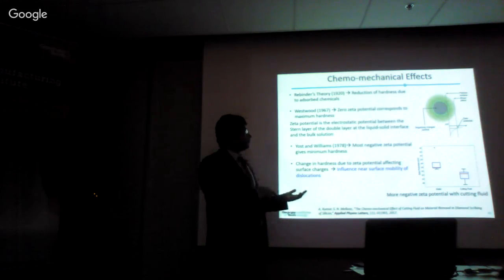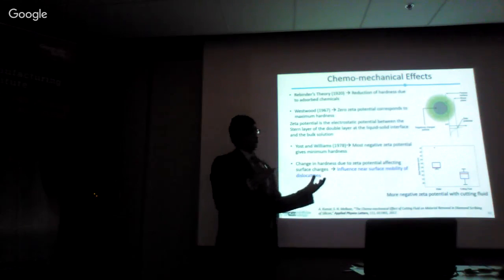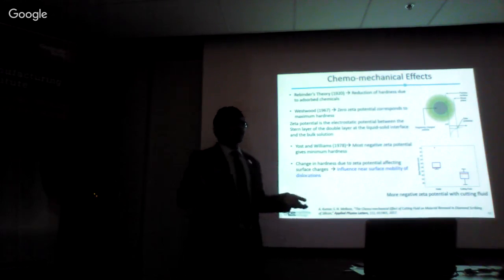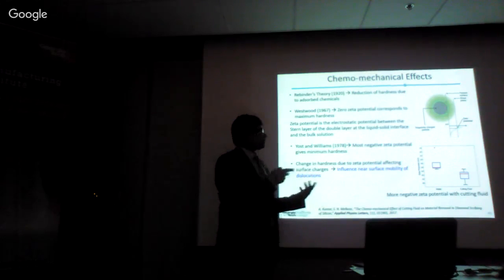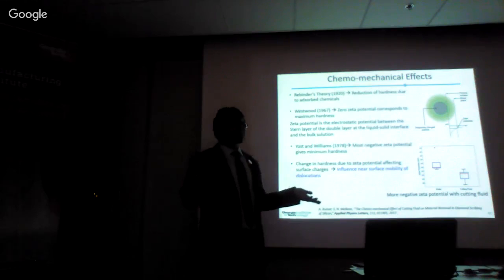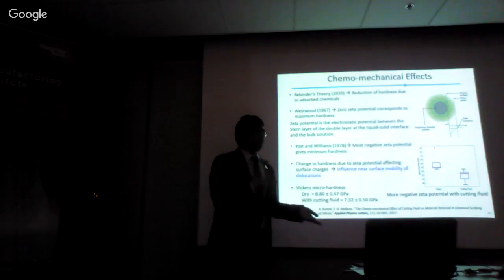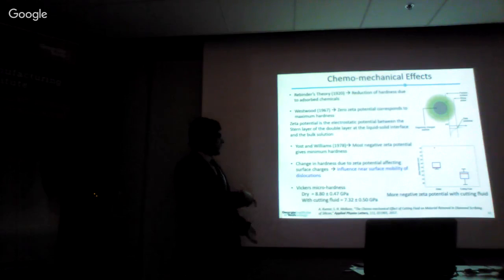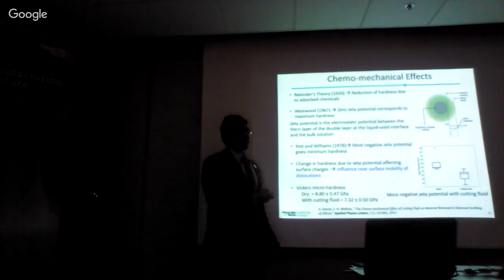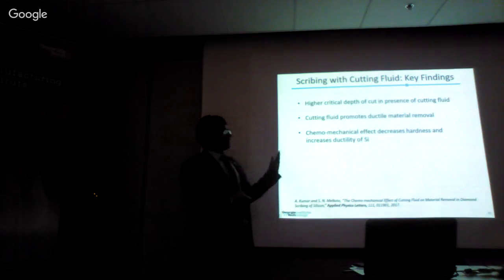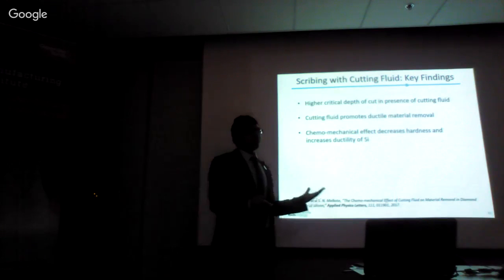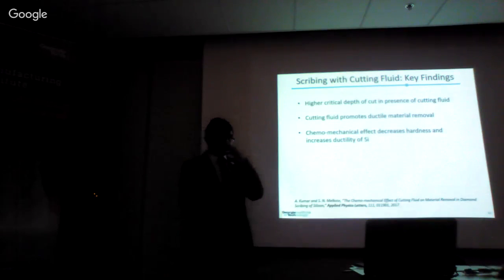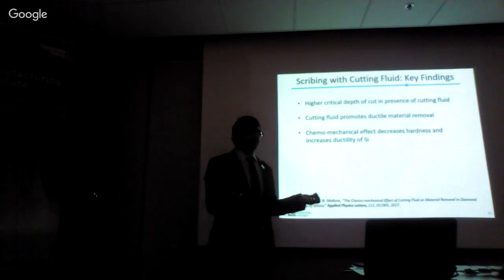the dislocations move. We found the zeta potential of the cutting fluid was more negative when we did zeta potential measurements of silicon ground powder suspended in the cutting fluid versus silicon zeta potential when put in water. Water is a proxy for the lab air, which is not very dry because there is always moisture in air. And we also found by Vickers hardness indentations that using the cutting fluid, the hardness is lower compared to using the dry conditions. So this explained our results that using the cutting fluid, we have a higher critical depth of cut, which means it promotes ductile mode material removal while using the cutting fluid.